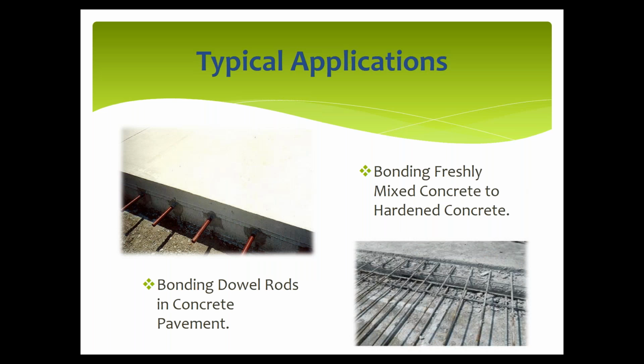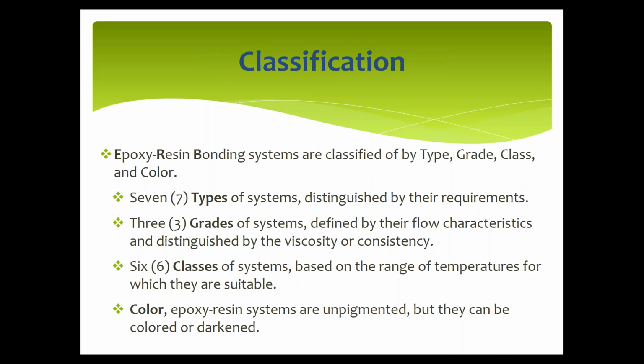Another typical application is bonding dowel rods in concrete pavement, and bonding freshly mixed concrete to hardened concrete. Classification as defined in this program, according to ASTM C881, is into type, grade, class, and color. Seven types of the system are distinguished by their requirements. There are three grades of the system defined by their characteristics, the viscosity and consistency. There are also classes of the system based on the range of temperature in which they are suitable. We'll be discussing the color of the epoxy resin system. They are unpigmented, but they can be colored in a darkened color.